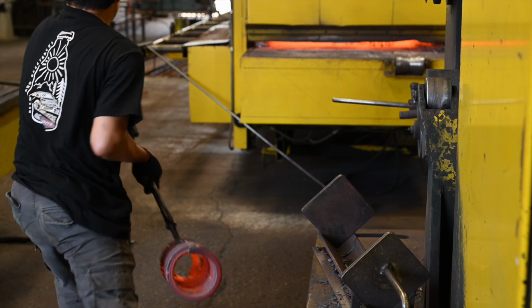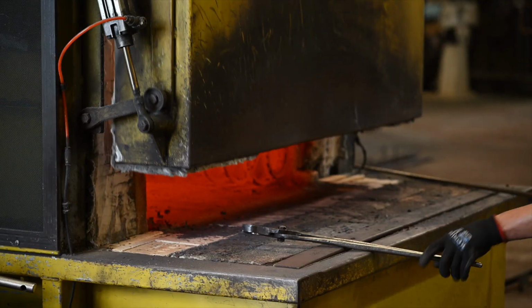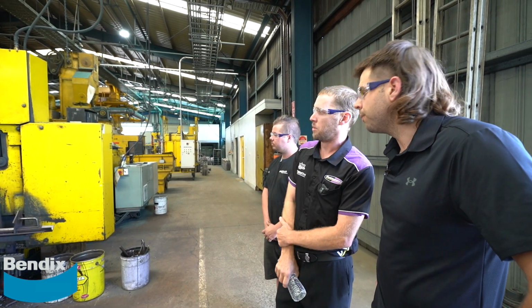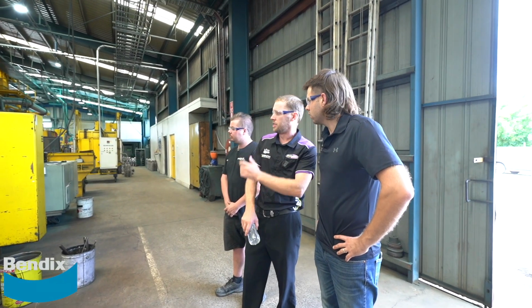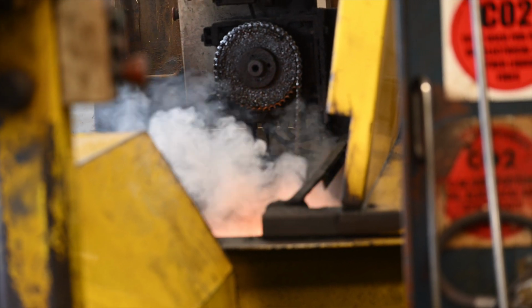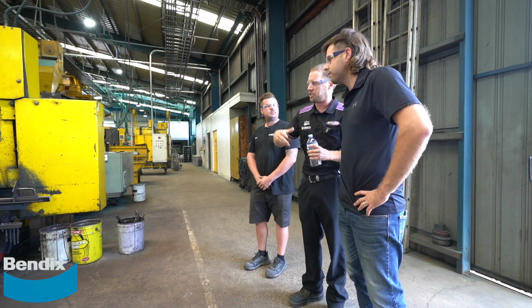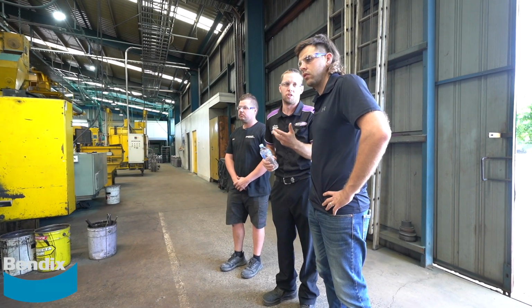What we want to do is actually wind them hotter than what we put them finished at. What that does is allow us to scrag the coil at a later date and get all the sag out of the coils. So we're actually winding them 20 or 30 mil higher than we want. We're at about 900 degrees here as they come out of the furnace. Throw them into the reheat furnace, and then into the quenching oil. That gives us a hardening process, which takes the steel from not quite mild steel, it's still a bit harder than mild steel, and then into the hardening process, which just rearranges the grain structure and the molecules in the steel, and that's what gives us the hardness for the spring steel.